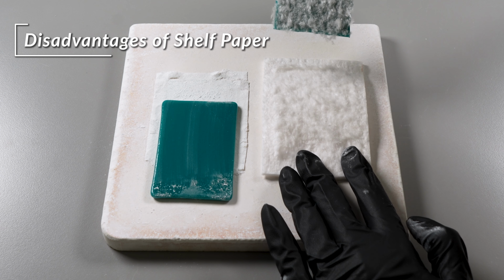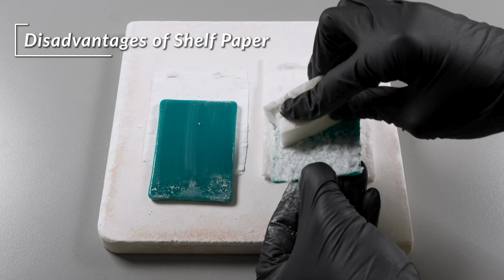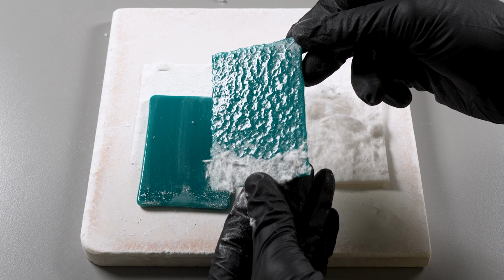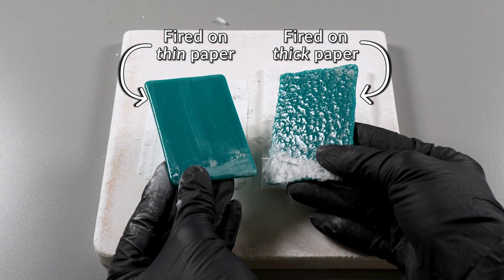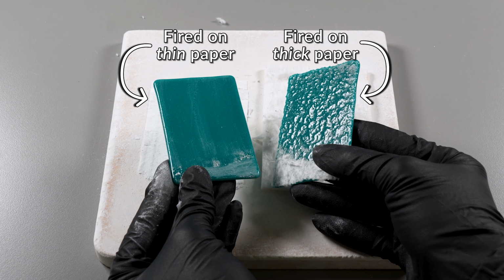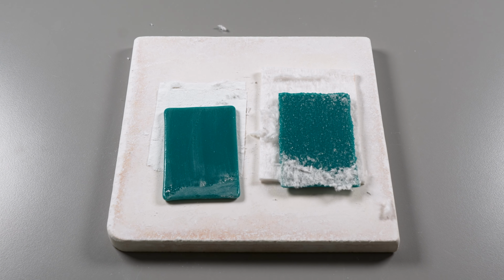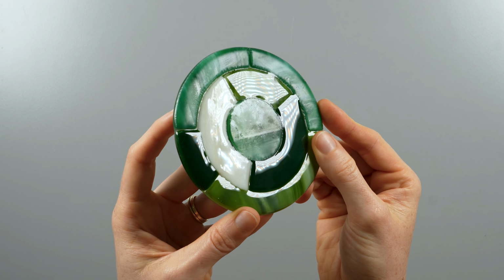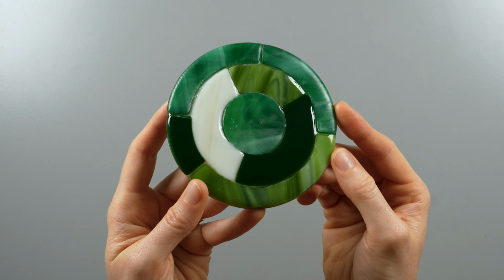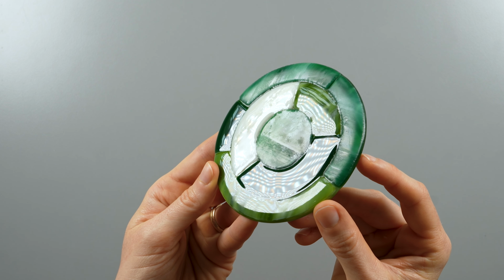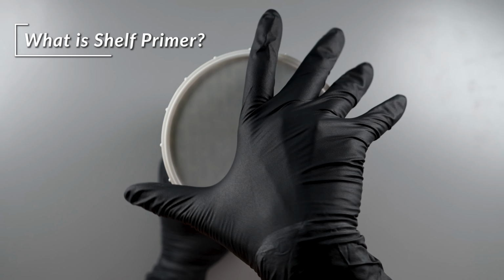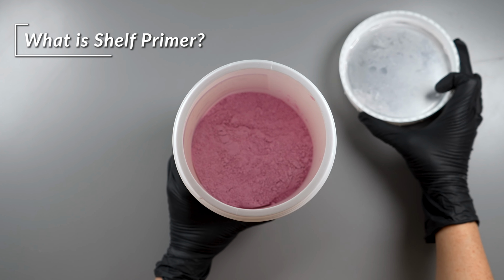One potential disadvantage is that thicker fiber papers almost always leave a slight visible texture on the glass surface post-firing. Since some material burns off of fiber paper at high temperatures, it may also introduce risk of devitrification, as we saw in Lesson 6. An alternative separator to shelf paper is shelf primer.